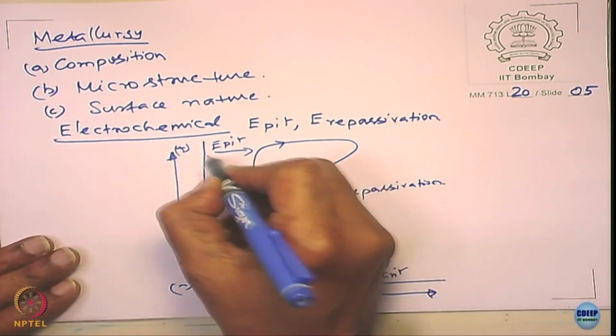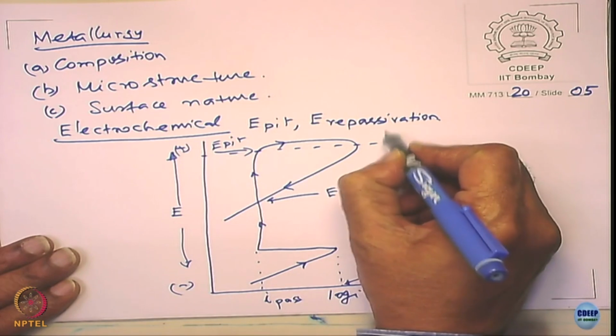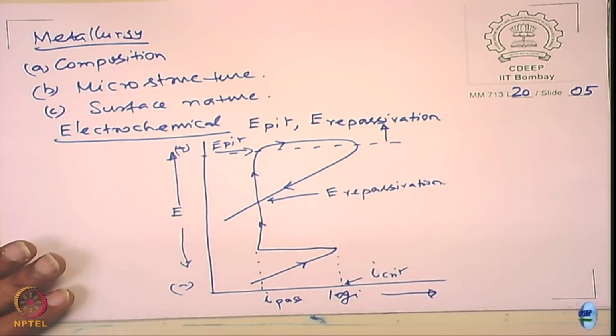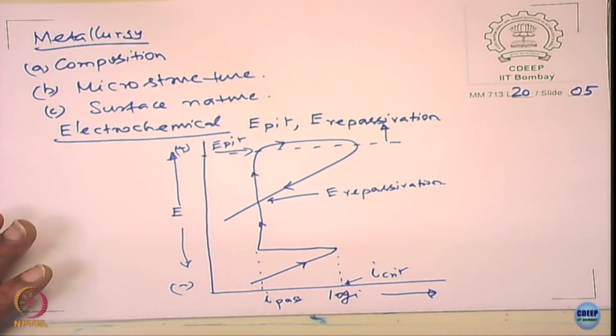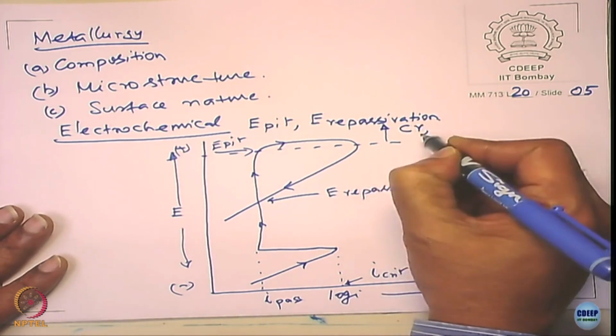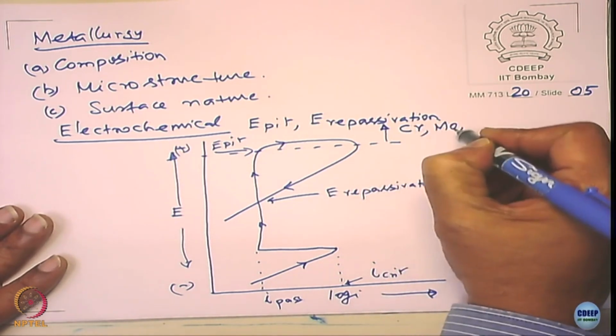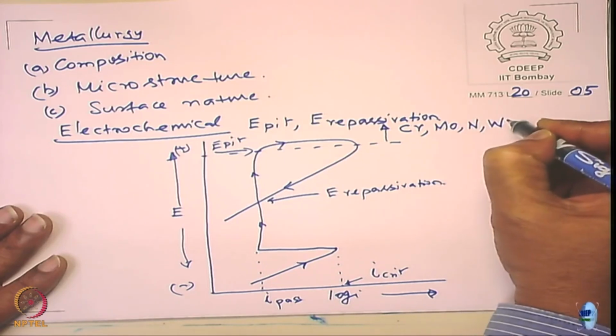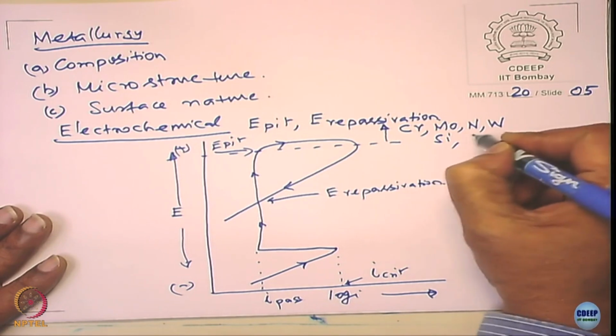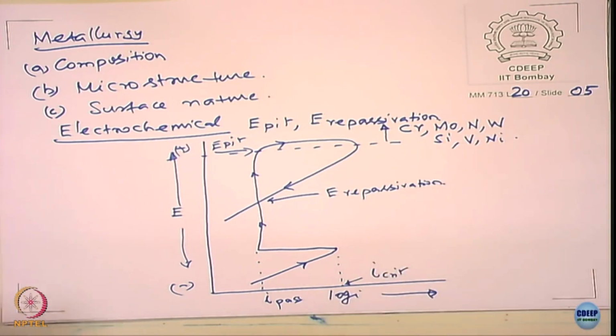Now let us look at the elements that can affect this. The elements that move up the E pit are going to improve the pitting resistance of the stainless steels. So what are these elements? These elements are chromium, molybdenum, nitrogen, tungsten, silicon, vanadium and nickel. So these elements increase the pitting potentials. So when you increase the pitting potential, that means the initiation tendency of the metal to pit is reduced.